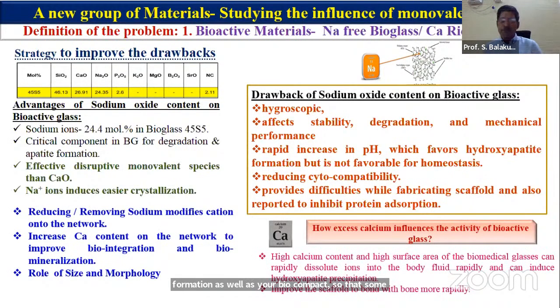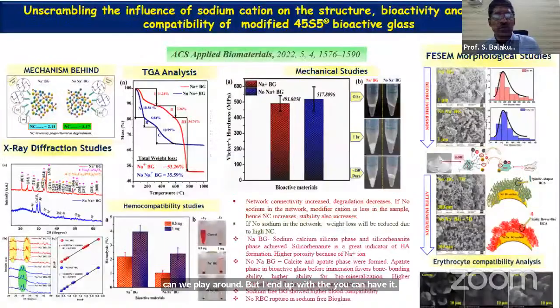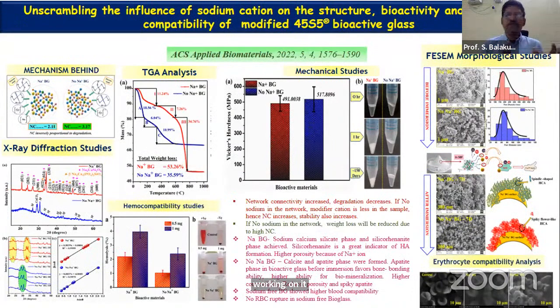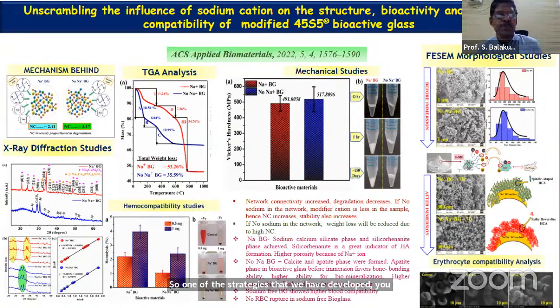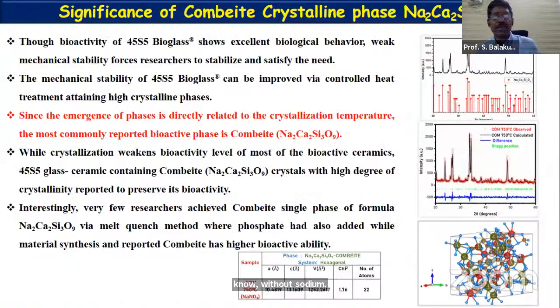Presently we are working on how you can use excess calcium, what the activity is on that, and whether we can trade off the calcium phosphate ratio, which should be 1.67. So we can play around, but at the end of the day, you can have it. Those are the two strategies we are working on. One strategy, without sodium, was recently published in ACS Biomaterials, and another material that we are working on is